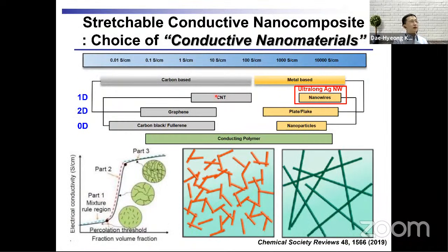So we take a look at the conductive rubber, and typically conductive rubber consists of two components: an elastic rubber matrix filled with conductive fillers. In the case of conductive fillers, there are several candidates, such as carbon-based materials such as CNT or graphene, conducting polymers, or metal-based nanomaterials. And as you can see, the silver-based nanomaterials show the best conductivity among all materials.